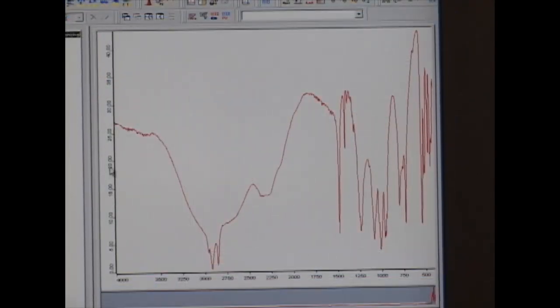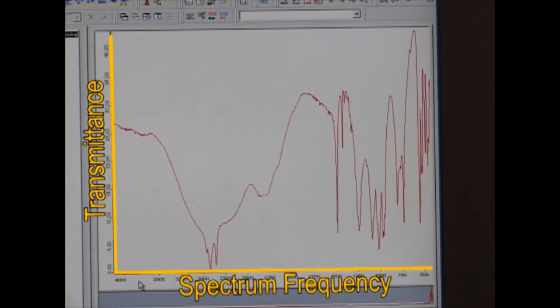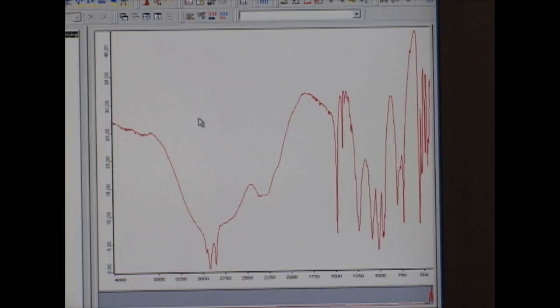On the Y axis, we have the transmittance, and on the X axis, we have the range of the spectrum or the wave number in centimeters inverse. These peaks are specific characteristics of different vibrational modes on molecules or vibrational modes of the bonds. Specifically in this area, between 2900 and 2800, this is characteristic of the CH2 stretching of symmetric and asymmetric vibrational modes of carbon bonded to hydrogen.